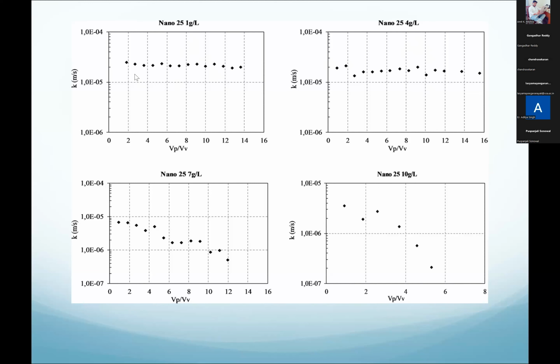So you look at this: if the concentrations are low, permeability is not changing. But if you have a high concentration suspension, the permeability is significantly lower. That's one thing you have to worry about. So you cannot use high concentrations. Then you will plug up the pores and hydraulic conductivity decreases. You cannot even flush anything. So you need to optimize the iron suspension concentration so that the permeability does not change.